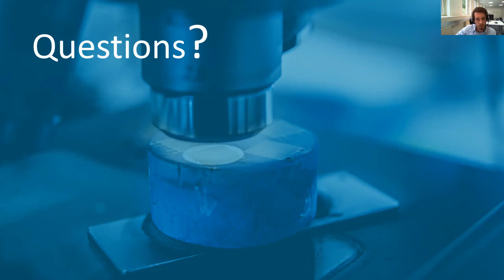Then the next question is from Wolfgang Käfer: does your CT allow you to look inside the parts, for example to see cavities? Yes, of course. The CT scanning that we are performing usually has a voxel resolution of, I think, 66 micrometers. So basically we're able to detect every porosity that is bigger than 200 micrometers in diameter. This is for the standard CT scan.